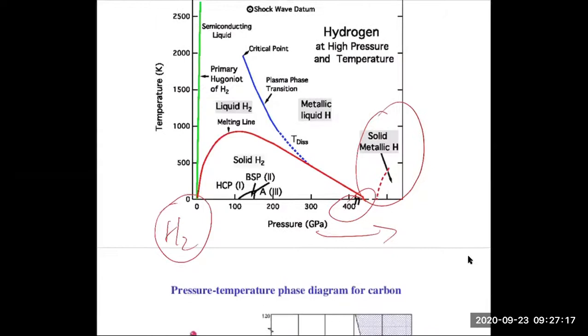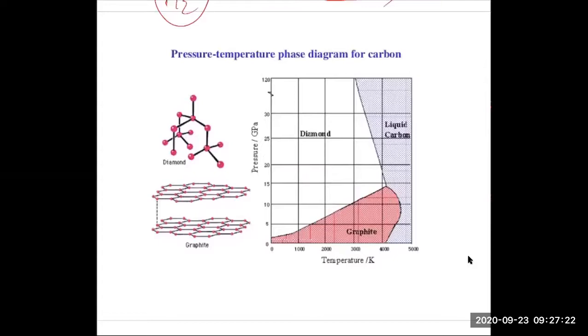Okay. Now the phase diagram with the largest discontinuity in value across the phase boundary. As you go from here to here, this is carbon. There is not only a delta V and a delta S, but there's also a delta dollar. Because of course graphite is pretty dirt cheap and diamond is not. As you can see from the phase diagram, graphite is the low temperature, low pressure phase, but diamond is the high pressure phase. It has considerably lower molar volume than graphite, which is why it's the high pressure phase.